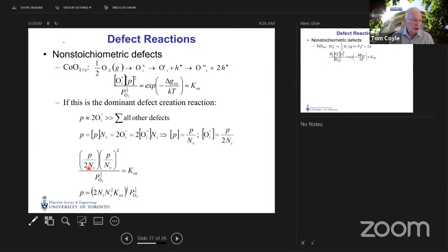The number of interstitial sites, which we can calculate, the number of vacant sites, which we can calculate, and the oxygen partial pressure. So bottom line, the concentration of holes resulting from this defect creation reaction is given by a constant multiplied by the oxygen partial pressure to the 1/6 power. So basically we're predicting that the hole concentration varies as oxygen partial pressure to the 1/6.